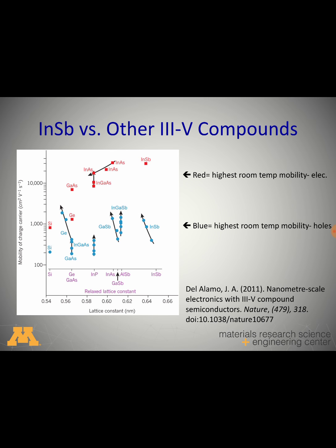And this is data pulled from materials that were measured and tested at 300 degrees Kelvin, or about say 80 degrees Fahrenheit, to give you a bit more of an idea. We can see everything highlighted in red here: gallium arsenide, germanium, indium arsenide, these other compounds, and they have their different mobility rates. But we can see here on the far right, as I mentioned, indium antimonide has the highest electron mobility rate out of all these materials.